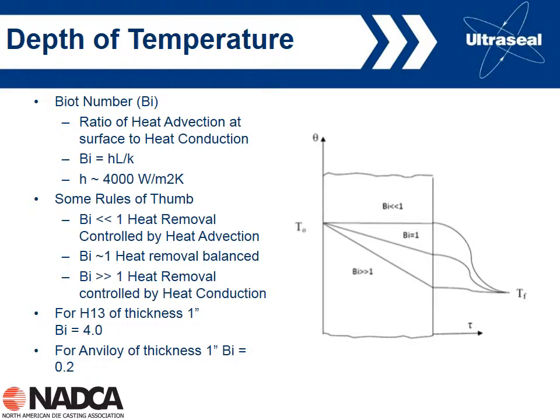So here we're talking about the Biot number. We're not going to go into all this information here, but this is interesting information if you want to look it up later. Let's focus on the diagram on the right. If the Biot number is very, very small, much less than 1, then we basically get this temperature profile shown here. If the Biot number is very large, down here, then we get more of a gradient through our die material. So for a 1-inch thickness of H13, the Biot number is about 4, which is obviously much greater than 1, and so we get this kind of data shown here.